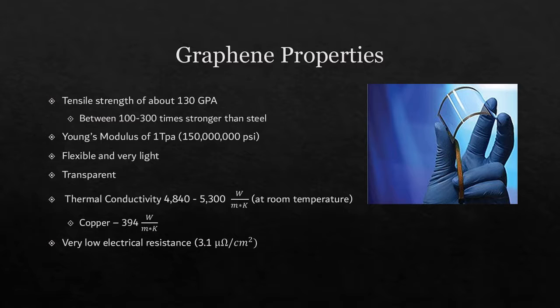Graphene has very many interesting properties. To start, it has a tensile strength of about 130 gigapascals, which, depending on the type of steel you're looking at, can be between 100 to 300 times stronger. It has a Young's modulus of 1 terapascal, which is equivalent to about 150 million psi. Graphene is also very flexible and also transparent. This can be seen in the image to the right of a technician who has produced a layer of graphene and is bending it, and you can also see through it.